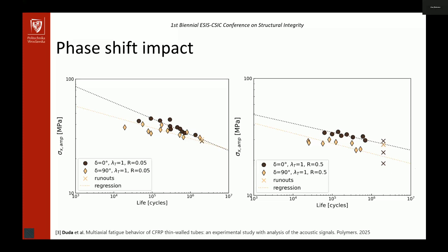And in general, the fatigue life results in lower life. Moreover, this is an important point: those S-N curves are plotted for the geometrical stresses, sigma x amplitude. We see in both cases the same effect for R equal 0.05 and for R equal 0.5.